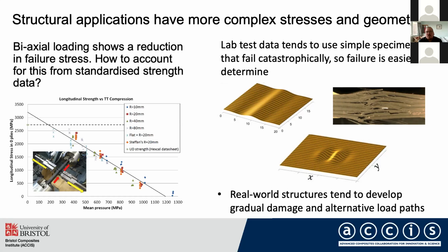So if we refer to lab scale tests, we tend to use quite simple specimens, and this looks at an example of a compression failure of a laminate with a wrinkle in it. And in the lab scale specimens, we would tend to make that prismatic, which in turn will lead to a very catastrophic failure, which you can see from the photographic image on the right.